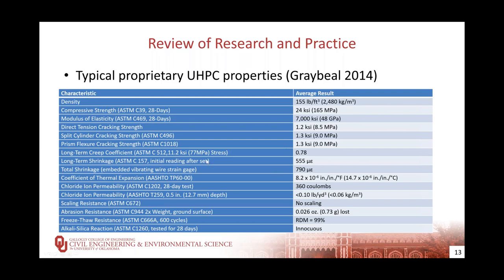Typically, we're going to get a compressive strength for these materials somewhere around 24,000 PSI, a direct tension cracking strength just over 1 KSI, so about 1.2 KSI, split cylinders and flexural cracking strengths, or MORs, modulus of rupture tests, lead to about 1.3 KSI cracking strengths. We have a very low chloride ion permeability for these materials. Some of those you have to test without the fibers because of electrical resistance. And then very good freeze-thaw resistance for UHPC, just in general.